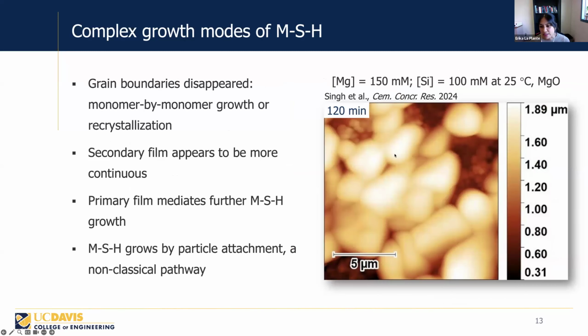And then zooming in on one of these longer reaction time samples, we notice that the grain boundaries start to disappear. This could happen through monomer by monomer growth or through a recrystallization process. It also appears that the secondary film is more continuous than the primary film, which suggests that the primary film mediates further growth. But importantly, what this evidence shows us is that MSH grows by particle attachment, which is a non-classical pathway for precipitation.